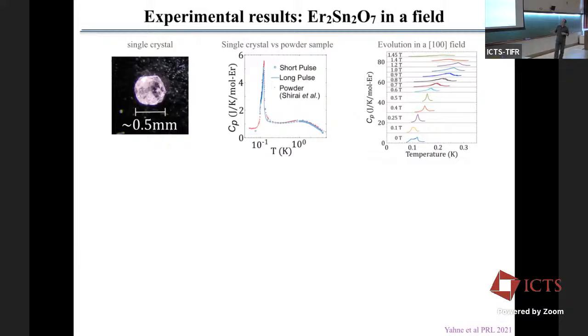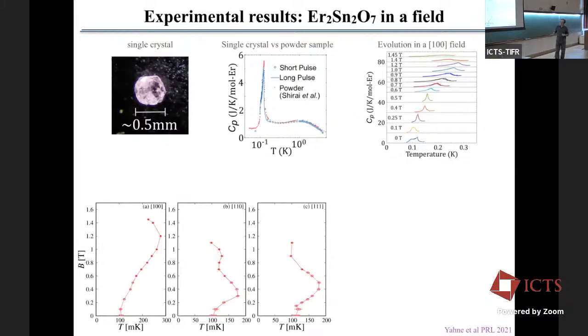Then Daniel did specific heat measurements, so with short pulse or long pulse cooling. And you see that we have a nice peak at low temperature in zero field. And as you increase the magnetic field, you see as this peak goes up, goes up, goes up, and then at some point it starts to go down.